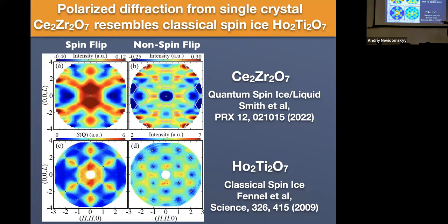You get the snowflake-like pattern where you have these things here in the measurement of holmium titanate, they have these things that are called pinch points. So the diffuse scattering, you've got this blobby diffuse scattering, and it comes together and just touches at a single point. And that's referred to as a pinch point. And we also get a pinch point in our measurements here, right there, but it's a fuzzier version of the pinch point. And once again, whoever was asking that earlier question, you can see that it's not present along the HHH directions.